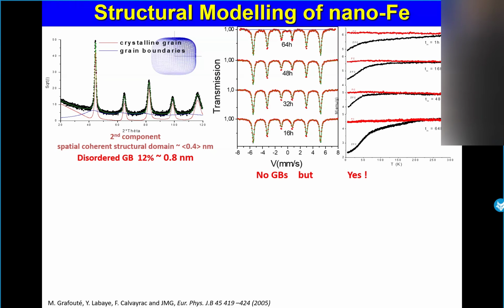Okay? Doing Mössbauer spectra, no changes. Oh, very strange. And of course, it could be possible to see some changes by increasing the temperature. But if we increase the temperature, we could also modify the nanostructure. So it was a problem. And by decreasing the temperature, no changes. So from X-ray diffraction, it was possible to estimate both components. And from field cool, zero field cool measurements, yes, there were grain boundaries. So, since by Mössbauer, no grain boundaries.